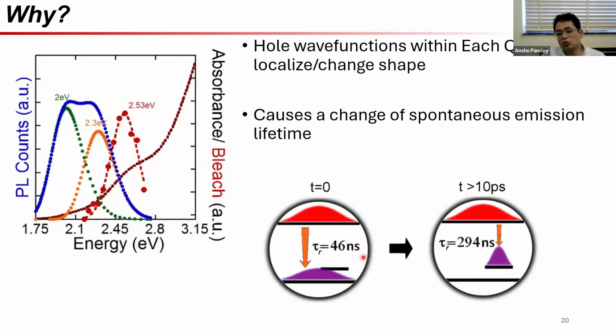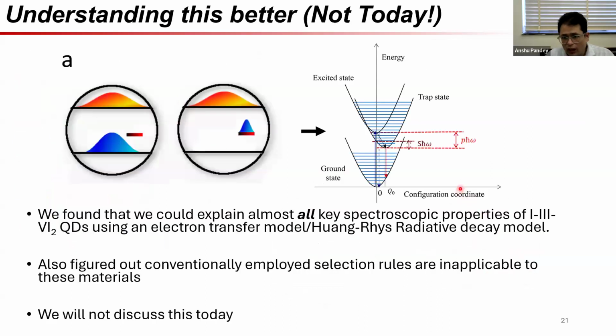We are seeing this smooth change in the entire sample from a radiative lifetime of 46 nanoseconds all the way going to 294 nanoseconds. Even though it's happening in the same material, other properties are remaining roughly unchanged. We are not seeing major changes in the material's emission; everything else is almost imperceptible, but its lifetime seems to be changing drastically. And that is the really, really weird observation over here. So again, why is that happening?